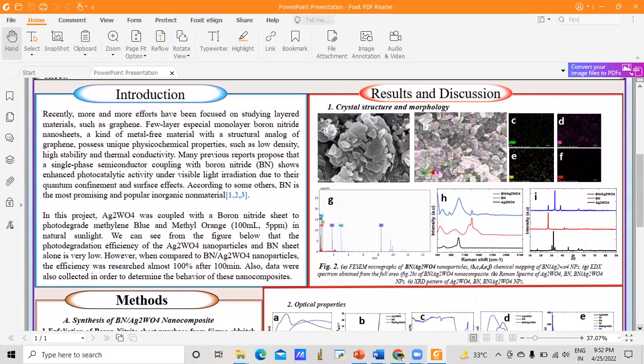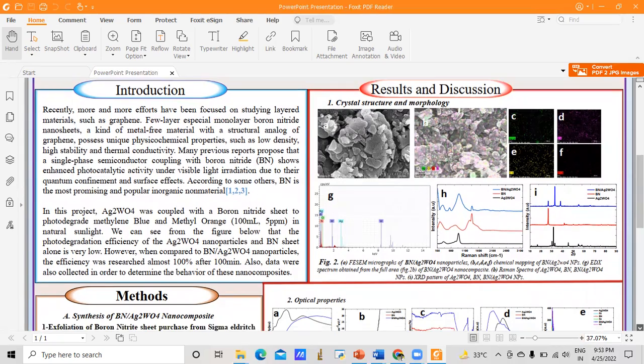So in this project, Ag2WO4 was coupled with boron nitride sheet to photodegrade methylene blue or methyl orange in natural sunlight. And we can see from the figure below that the photodegradation efficiency of either Ag2WO4 nanoparticles or BN sheets alone is very low. However, with the BN-Ag2WO4 nanocomposite, the efficiency reached almost 100% after 100 minutes. Also, data were collected in order to determine the behavior of this nanocomposite.